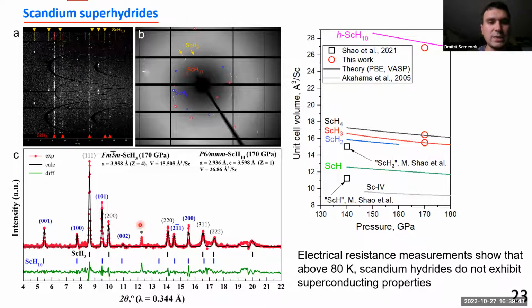except with two exceptions. One peak is still unexplained. I don't know how to explain it. And one peak is still missed. The rest of the peaks are more or less okay, and we can state that 90% of the diffraction pattern is explained by this combination of two phases, scandium H3 and scandium H10.